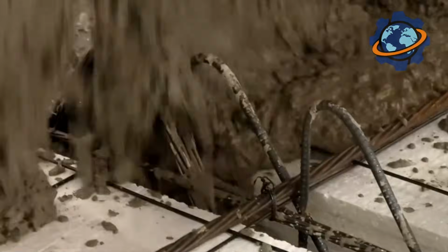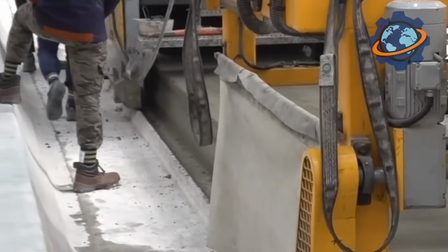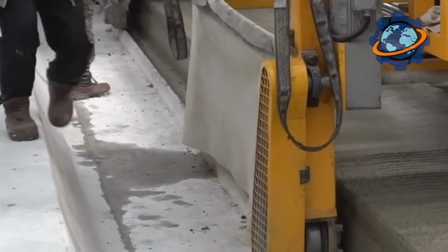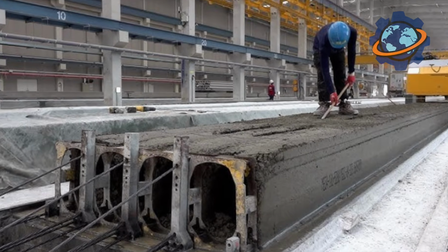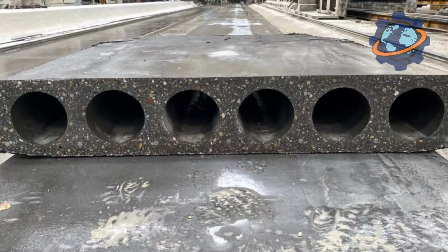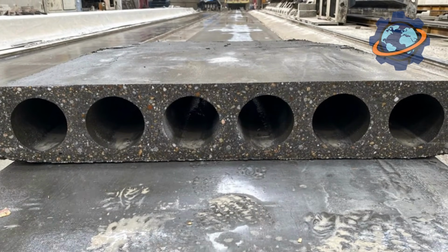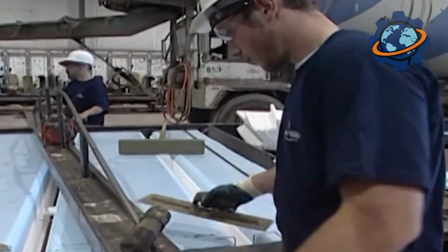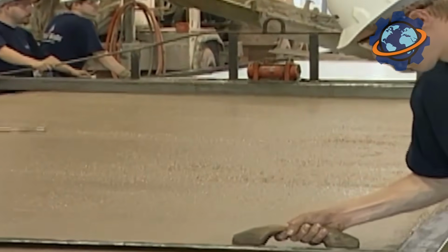This isn't just building, it's a conveyor belt running at a speed unthinkable for traditional, pour-on-site concrete. And now for the main trick, the hollow cores. These holes inside aren't just for looks. They slash the slab's weight by almost 50% compared to a solid slab of the same thickness and strength.